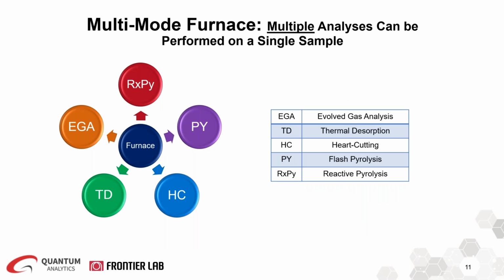So now let's talk about the multi-mode pyrolyzer and how it works. As the name says, using the multi-mode furnace, multiple analyses can be performed on a single sample. This is really another advantage of the multi-mode pyrolyzer, where its furnace can be used for other analytical techniques in addition to flash pyrolysis. In fact, the multi-mode pyrolyzer can be used for evolved gas analysis, thermal desorption, heart cutting, and reactive pyrolysis in addition to flash pyrolysis.